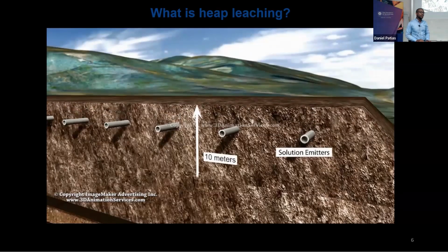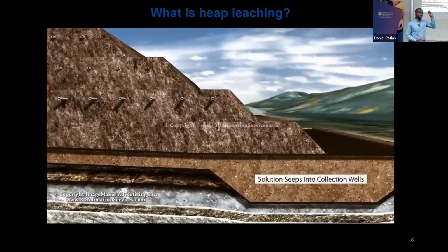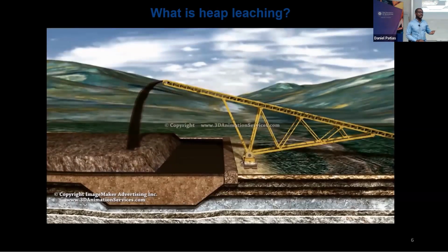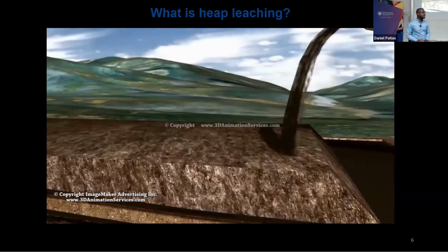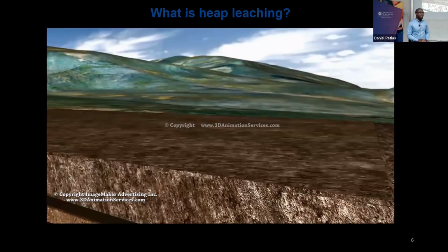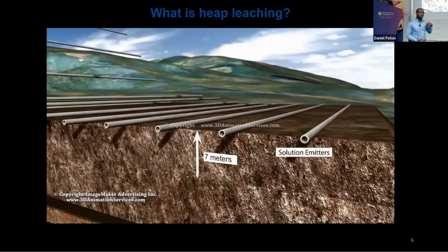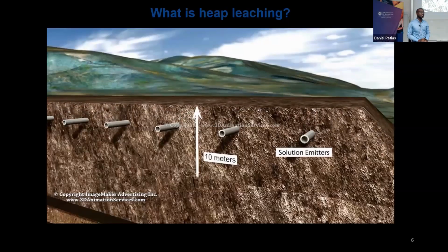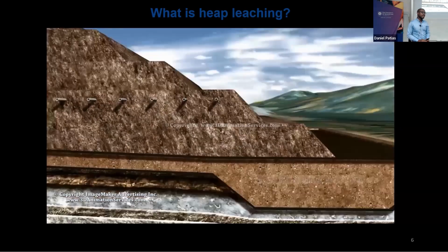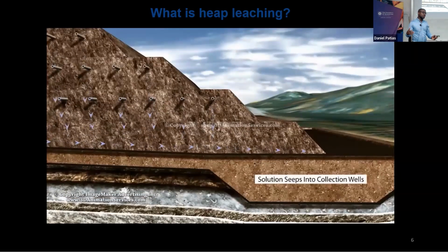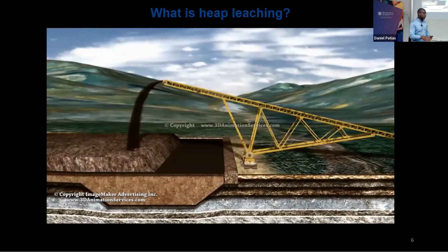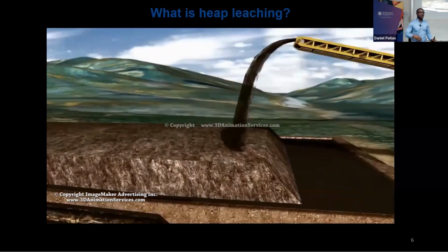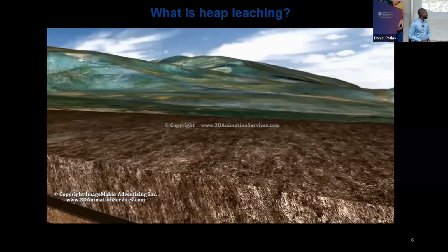In the case of copper, often it's acidic lixiviant from the top to the bottom. At the bottom, sometimes they have air sparges to help oxidation. Then your fluid trickles down from the top to the bottom, contacts your mineral of interest, in this case your copper minerals. It mobilizes the copper into solution, which is collected into a tank at the bottom, and then you get your copper for further refining and processing.